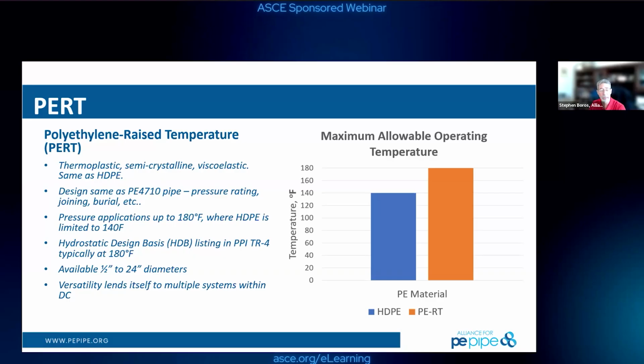Our normal HDPE that we see for municipal applications can be used up to 140 degrees continuous long-term use. PERT can be used up to 180 degrees continual long-term use. So even within data centers, that covers a lot of the heat loop systems that you're looking for, especially when you bring it from the CDU back out to the cooling towers. PERT could be perfect for that. In fact, it is used for that quite often. Again, it's available from 1/2 inch to 24 inch, and it lends itself to a lot of different applications for that. A lot of district heating, district cooling. That's where you see this little niche of PERT really shines.